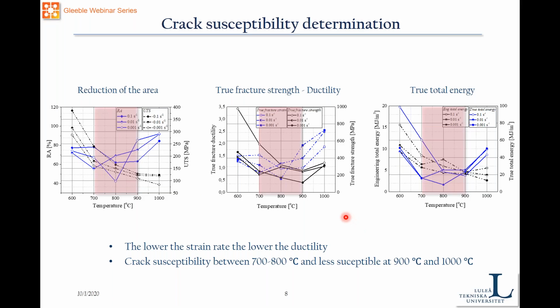So then what we can see here is that the true fracture strength is as well based on the reduction of the area, but it takes into consideration the true stress and the true strain at the fracture point. So then we can also see how the material is reducing its ductility, and the same in the true total energy. So we can say here that the lower the strain rate, the lower the ductility. So the effect of the strain rate is also playing an important role here.